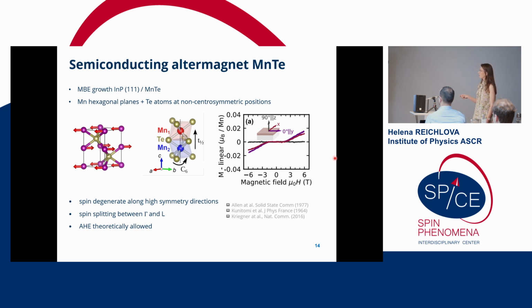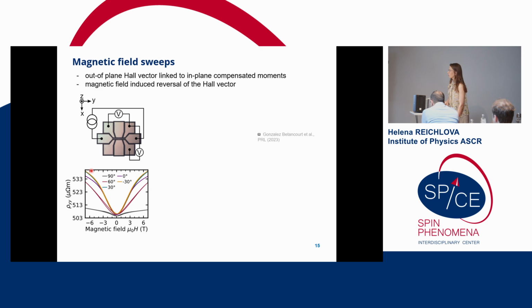At the same time, when we measure the magnetometry, we see that it is perfectly or almost perfectly compensated, with a vanishing net magnetic moment. And calculations, again from the Mainz team, show that the anomalous Hall effect is indeed allowed. So from manganese telluride thin films, we patterned Hall bars, and we measured the transversal and longitudinal voltage. As I showed you on the previous slide, the spins are basically in the plane of the manganese, but the Hall vector is out of plane, and it can be linked to the external magnetic field, so we can control it by an external magnetic field.